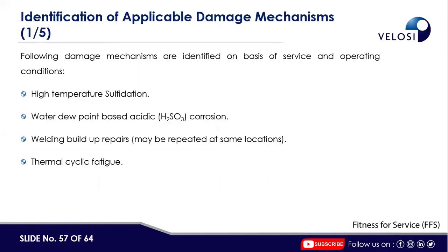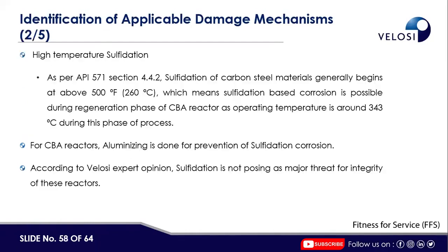The following damage mechanisms are identified on the basis of service and operating condition. High temperature sulfidation, when temperature goes to 343 degrees Celsius. Water dew point based SO2/H2SO3 corrosion, when operating under normal operation at a temperature of 127 degrees Celsius. Welding build-up repairs, which might be repeated, and thermal cyclic fatigue. These are the 4 major damage mechanisms which are required to be controlled while operating this equipment.